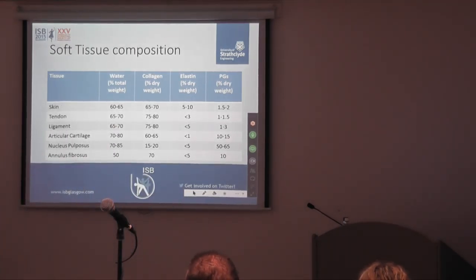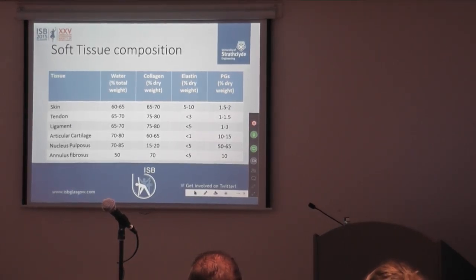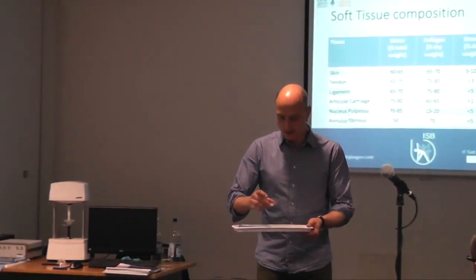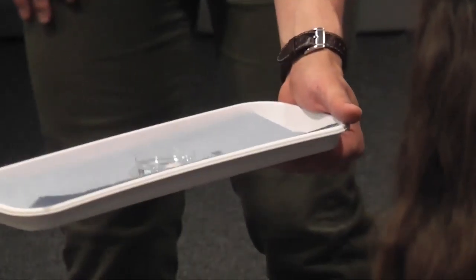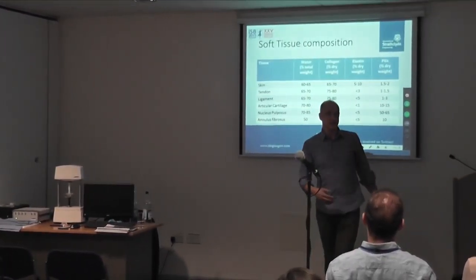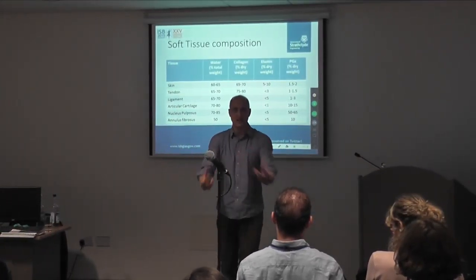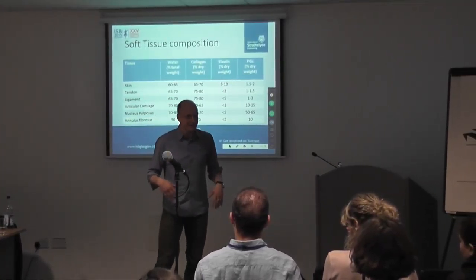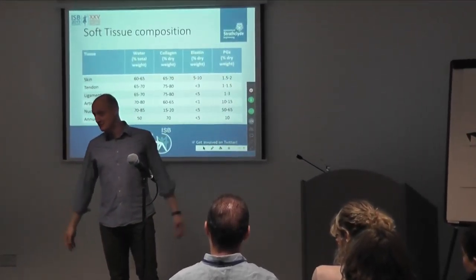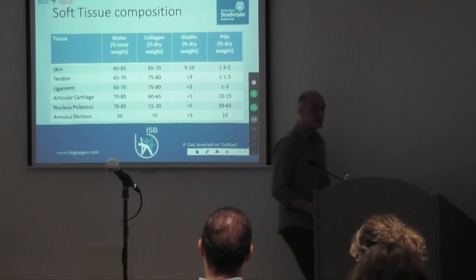I put a little bit of this nucleus pulposus in some water earlier, and it's just swollen up. Have a look. Generally it will keep on swelling up. It swells up to about four times its size. It just wants to suck up water, which is great if you're standing up for 20 hours a day and you go to sleep for 4 hours a night, because then your spine just sucks up all that water again. It just wants to suck things up, and that's due to the GAGs.